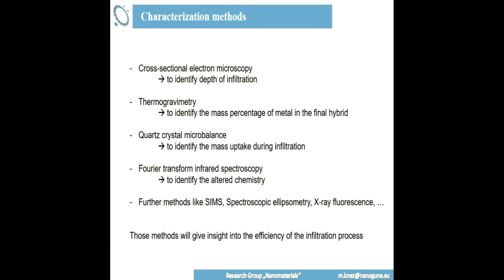So for characterization, if you want to see whether and how deep you infiltrate, again, cross-sectional electron microscopy is a straightforward way to do it. It's not so easy, but it's the best way. You make a FIB cross-section of your polymeric structure, and then you take a look either with a mass contrast, or EDX, and you will see how deep you get in.